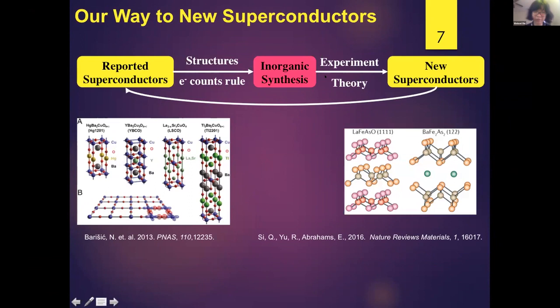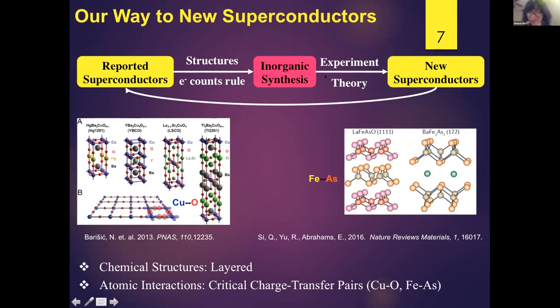Okay, I think a lot of the audience don't have a lot of physics background. But even just as a chemist, you look at these two structures, what do you see? I think one thing we can easily find is that they are layered compounds, okay? They're always layered compounds. That's very interesting. And the second thing: when we talk about cuprates and iron arsenides, a lot of people try to see, if cuprates work, how about nickel oxides, nickelates, cobalt oxides, iron oxides? It turns out that most of the time it's not working.